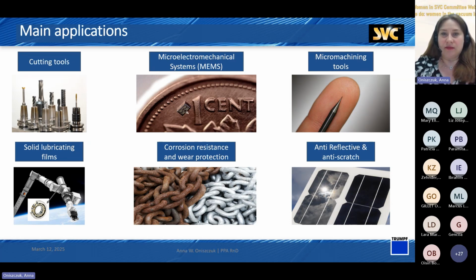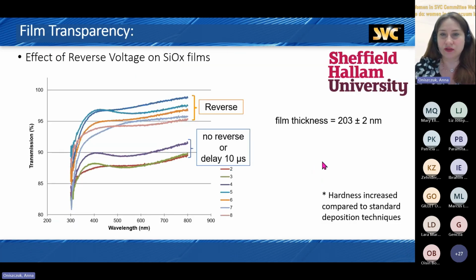Now, quite often we can see applications for microelectronics and micro tools, solid lubricants, anti-reflective and anti-scratch. For the anti-reflective and anti-scratch, I want to show you some of the results made at Sheffield Hallam University, where we investigated a silicon oxide film, and the hardness was increased compared to the standard technique. We investigated the influence of different parameters, like reverse and reverse delay, on the transmission. So not only can you increase the hardness, but you can also tune the optical transmission properties in order to get a very good protective top layer.